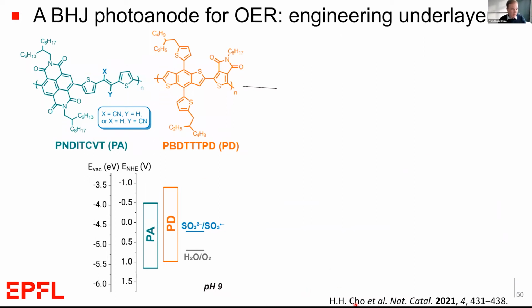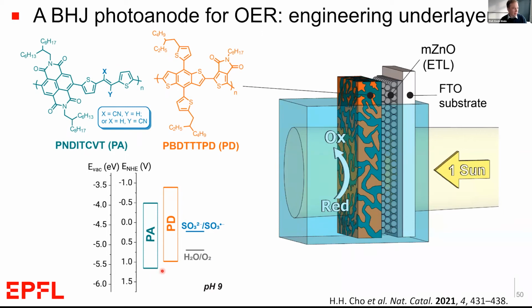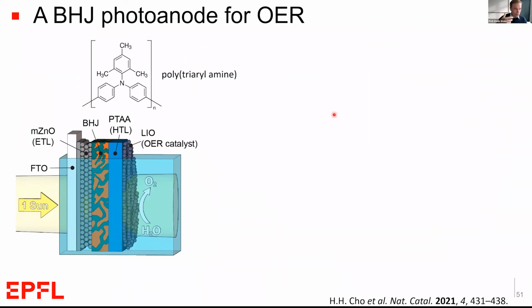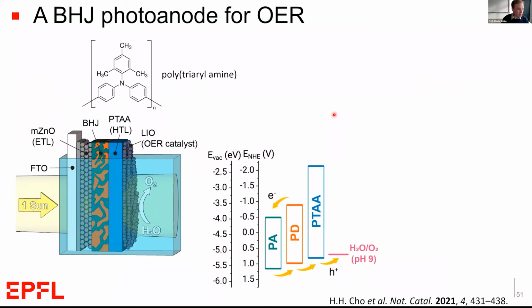And I also have to acknowledge Professor Cho, who developed a very impressive strategy to use this bulk heterojunction concept actually as a photoanode to make water oxidation in our lab recently. He engineered, first of all, the right materials that can achieve the right energy levels for water oxidation in these organic semiconductors. And he had to engineer this interface here with the substrate to increase the surface area using a mesoporous zinc oxide, which helps to achieve a more stable performance.